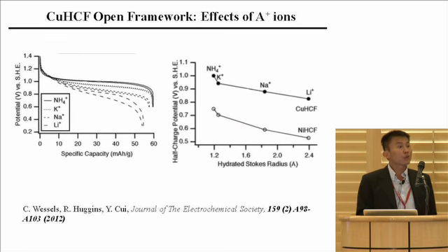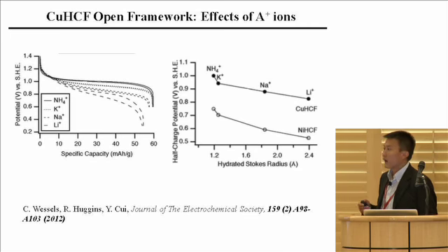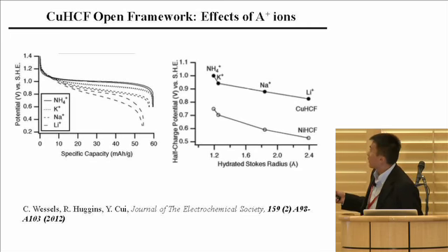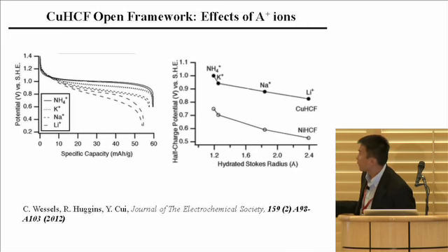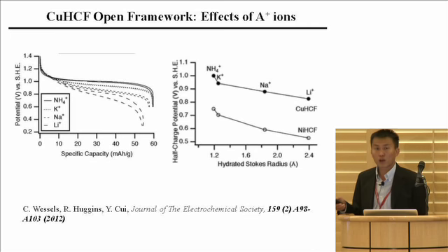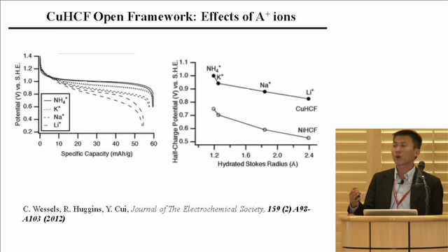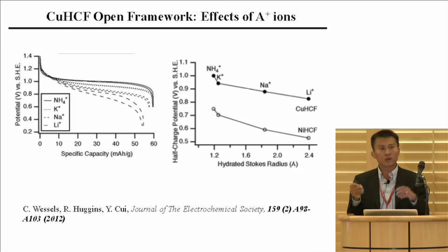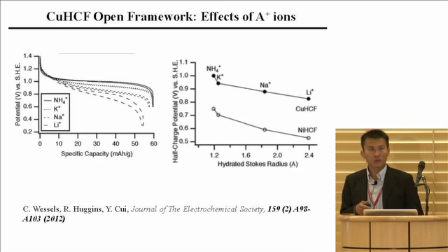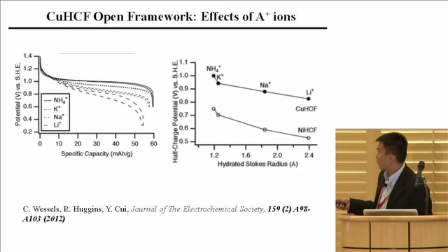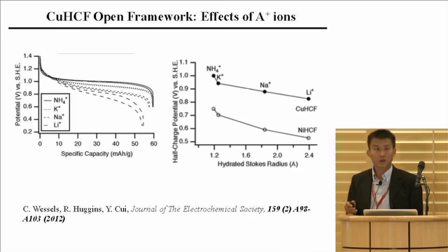You can also choose what cation you are going to insert. We talk about sodium and potassium. You can look at ammonium, you can look at lithium. They have slightly different charging potentials. When you look at lithium, the charging potential right here is lower. That's because lithium has a really strong solvation effect with water, and to strip off that solvation shell takes some energy. It actually makes it harder for these crystals to take lithium, so the potential needs to be lower.